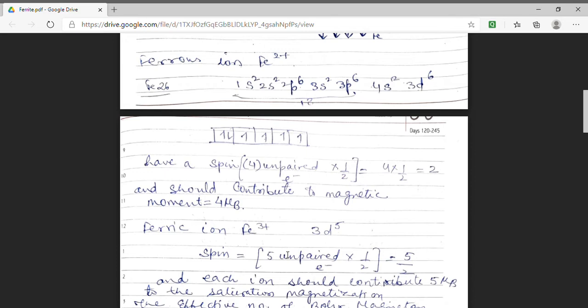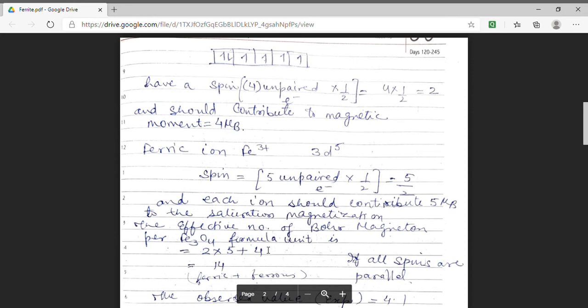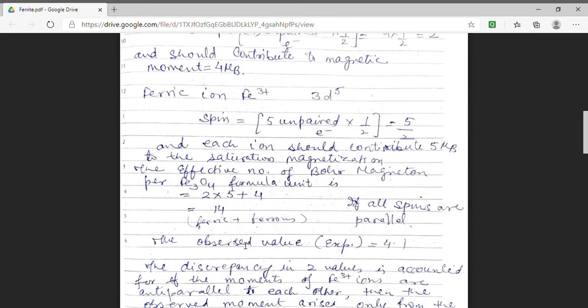So the total magnetic moment of magnetite Fe3O4, if all the ions — trivalent and bivalent — are parallel, then the contribution will be from 2 ferric ions (2 × 5 = 10) and the ferrous ion contributes 4, giving a total effective magnetic moment of 14 μB. This is the condition if all spins are parallel. But the experimental value of magnetic moment of magnetite is 4.1 μB, meaning there is a large discrepancy between the calculated and experimental data.